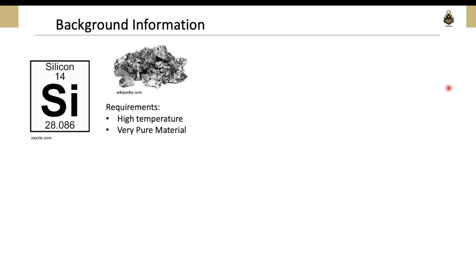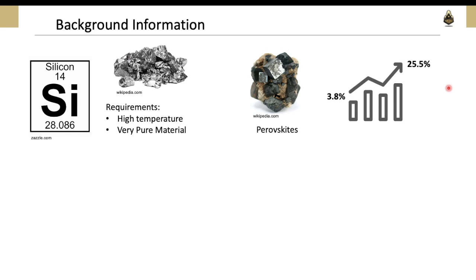In the past decade, promising light absorbing materials called perovskites have experienced rapid development. Within only 12 years, the power conversion efficiency of perovskite solar cells has improved from 3.8% to the most recent 25.5%, which rivals the 26.1% record efficiency of single crystal silicon solar cells that was achieved after more than 60 years of study. Impressively, here we're comparing devices made of polycrystalline perovskite to the ones made of single crystalline silicon.